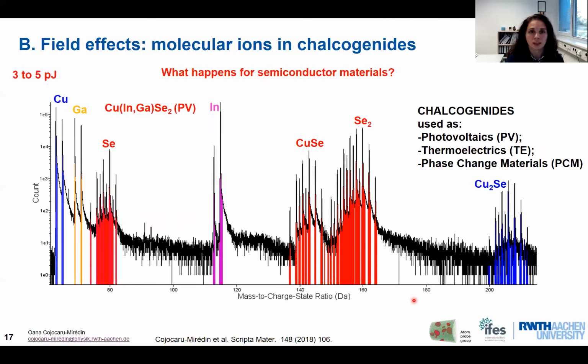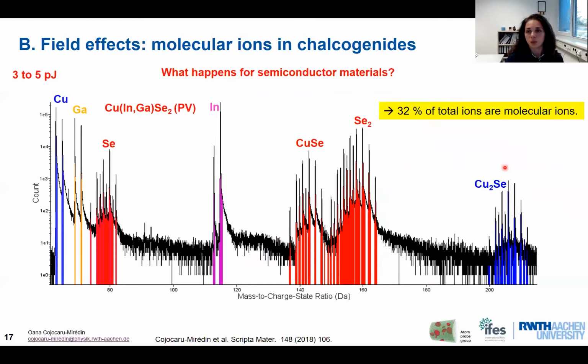So let's start with the copper indium gallium diselenide. This is a photovoltaic material. It is known to have a very high absorption, so it absorbs light easily, and it also photogenerates electron-hole pairs easily. But what we see on the mass spectra is a pretty high fraction of molecular ions, like selenium-2, copper-selenium, copper-2 selenium, and there are many other molecular ions at higher mass-to-charge ratios. If we then calculate the fraction of these molecular ions, we typically get about 32%.